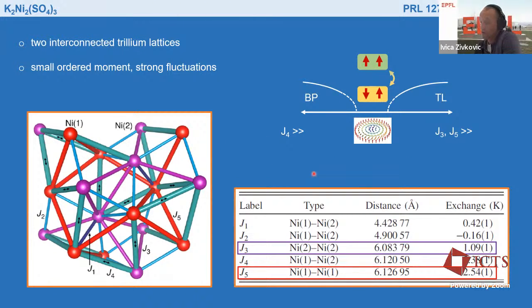But then, because the space group is non-center symmetric, everything is sort of chiral, everything is twisted. And in the manner of the analogy with skyrmions, the non-center symmetric space group is mixing up these singlets and triplets in a way that the ground state actually has a little component of the triplet state, which means that every singlet is dressed a little bit with a moment, so it's non-zero. These moments are then coupling into non-trivial lattices, which can be influenced in a non-trivial way by magnetic field, leading to a fully dynamical state.